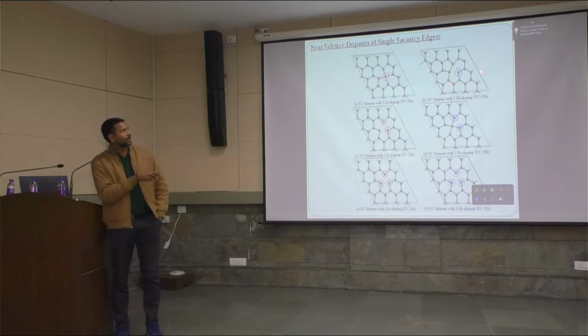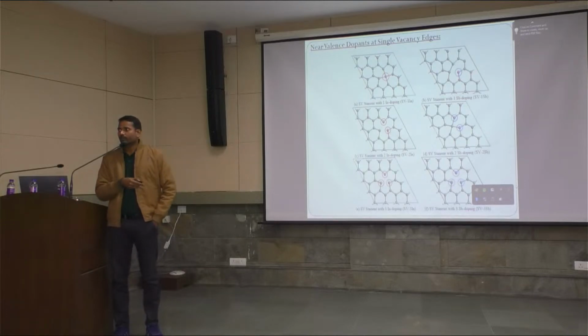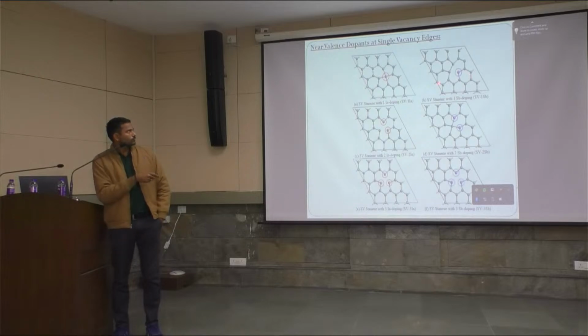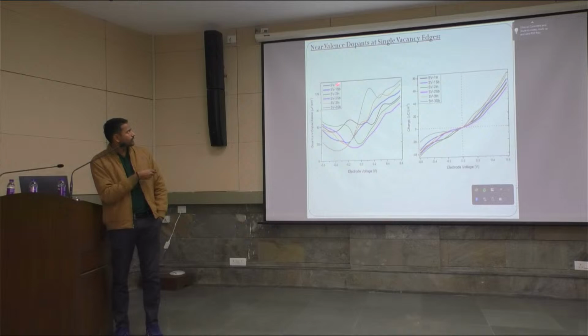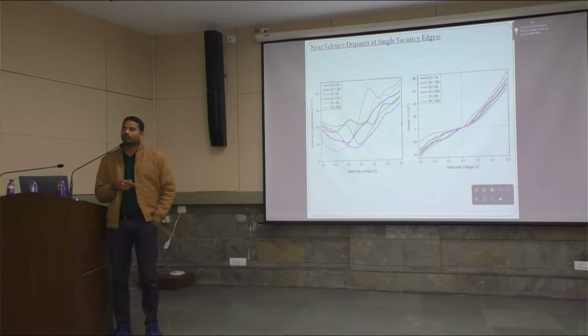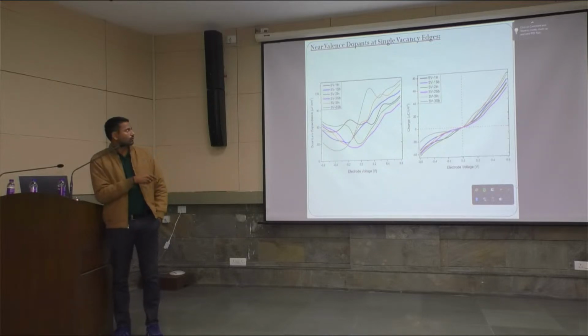And we have observed that antimony offers better thermodynamic stability in comparison to indium in stanene, because when we position antimony, the antimony can offer a lone pair, but indium cannot offer a lone pair. So we think this is the reason we are getting better stability for antimony in comparison to indium. And all these indium and antimony dopants offer the quantum capacitance on the positive side of the electrochemical window. This says all these dopant structures are suitable for the anode electrode of the asymmetric supercapacitor rather than the symmetric supercapacitor, because quantum capacitance peaks are observed on one side only. So we can say that these are suitable for the anode of an asymmetric supercapacitor.